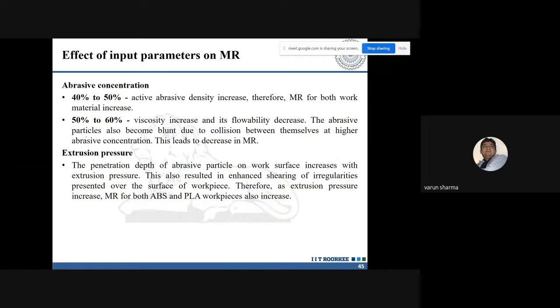Besides this, as your abrasive concentration increased from 50 to 60%, the viscosity increases and the flowability of that particular abrasive media within the upper and the lower cylinder decreases. And when it decreases, it results in more collisions. More collisions mean more bluntness of the abrasive particles. More bluntness of the abrasive particles primarily leads to decreasing material removal for that particular work material.